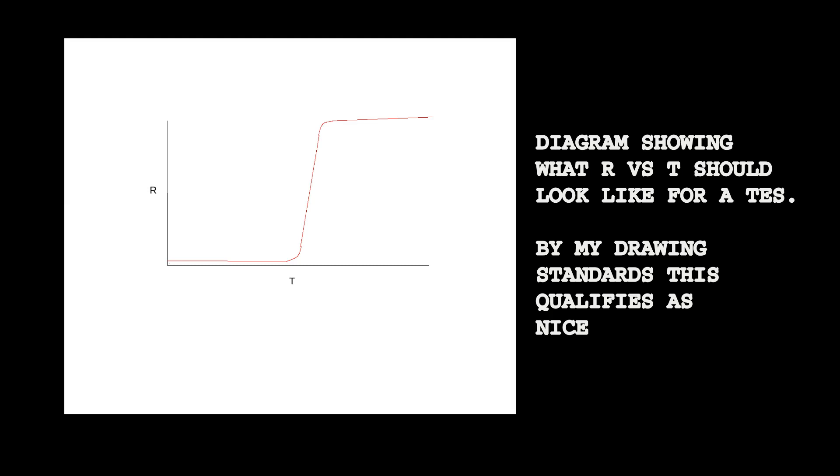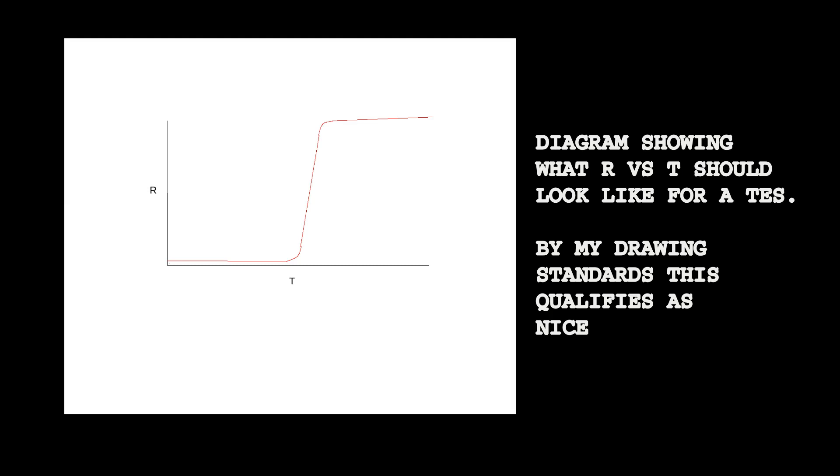I'll show a nice graph of this. Imagine putting a material that has this superconducting property right here in the middle of the superconducting transition, and then a photon hits it. It's a tiny change in temperature but an enormous change in electrical resistance. You'd have a really sensitive detector.